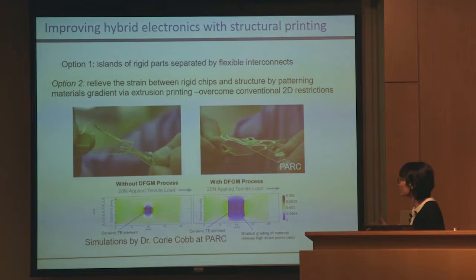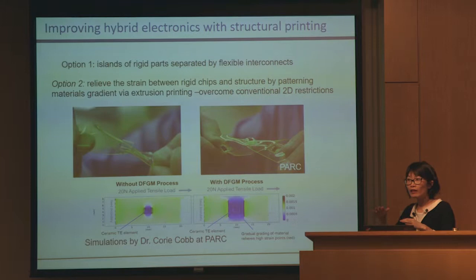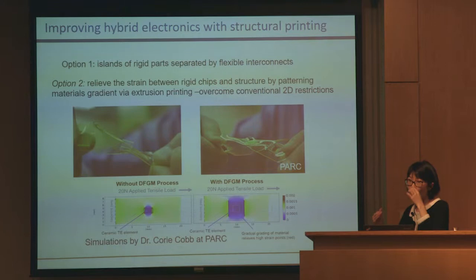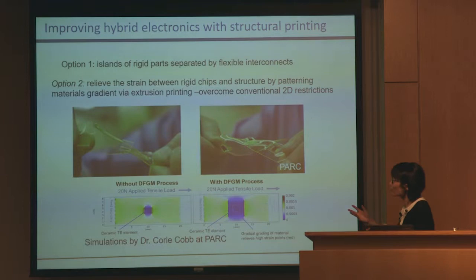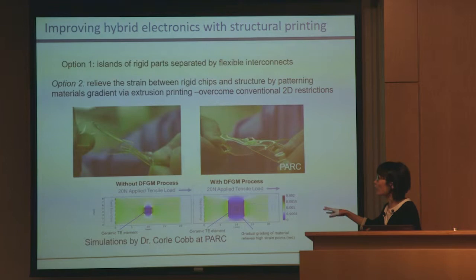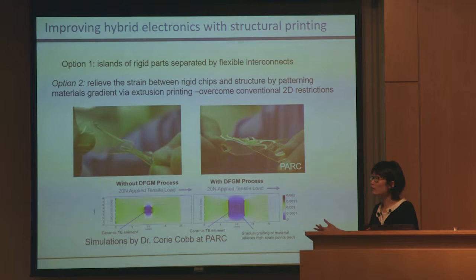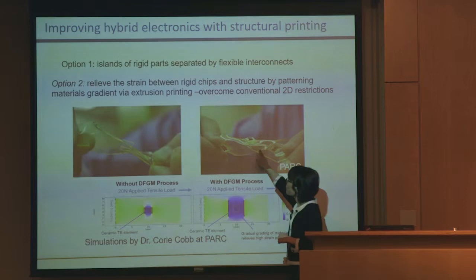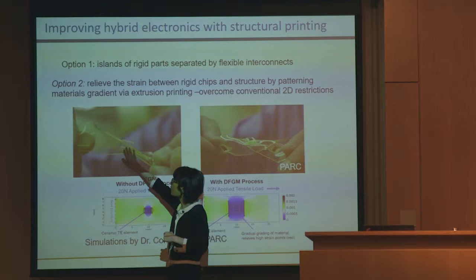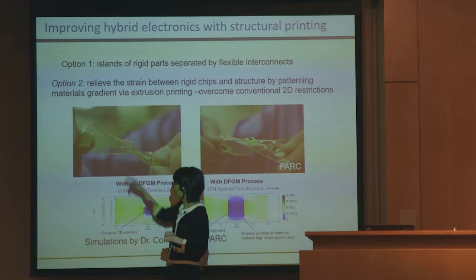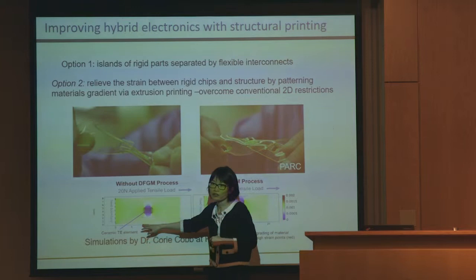You might have seen people now thin down dies and try to make the material as thin as possible so it would stick on flexible structures. But for us, we found that a lot of the advantage of packaged chips would be gone if you have to use bare die alone and thin it down, and that's much more processing. So we want to use off-the-shelf chips, and here this is glass, but we want to represent it as an off-the-shelf chip. Once we stick it on, the breakage point is always at the interface from the rigid area to the flexible area. The stress is just so high that that's where the failure always happens.